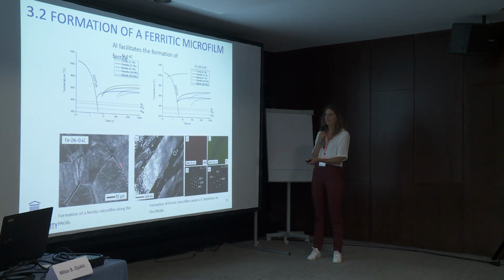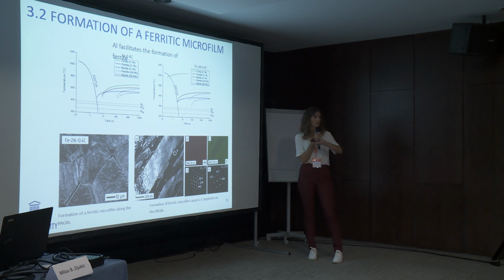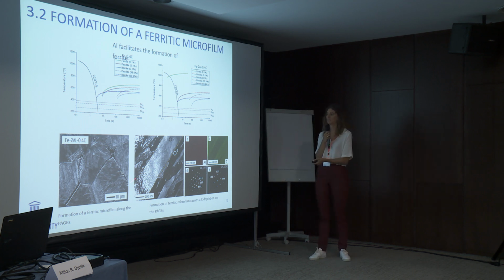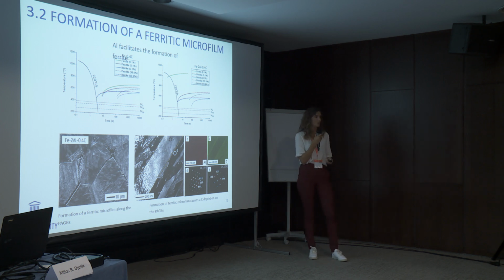Well, you can see here, we have martensitic grains, but along these martensitic grains, on the parent austenite grain boundaries, we really form this very, very small ferritic layer. A more detailed characterization by TEM, so we made FIB samples with TEM that contained this microfilm, and what we see there is it really has a clear BCC structure, and moreover it also has a carbon depletion.